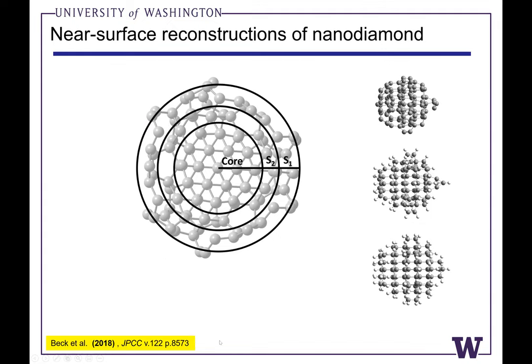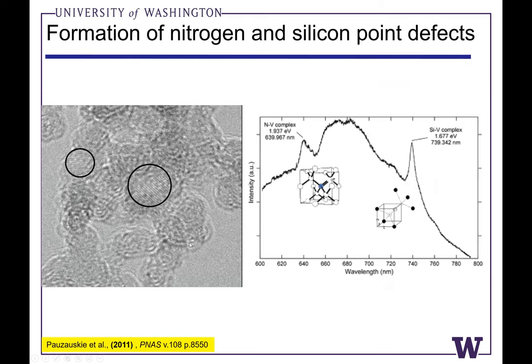This is a paper from a few years ago in collaboration with Xiaosong Li's group in the chemistry department, where we did some ab initio quantum cluster simulations to observe these sp2 type bonds forming on the surface of the diamond in vacuum, at least. We can also, using electron microscopy, zoom into these diamonds. You can take high resolution TEM images, and these are the 111 lattice fringes of the cubic diamond crystal lattice. You can see these 111 fringes.